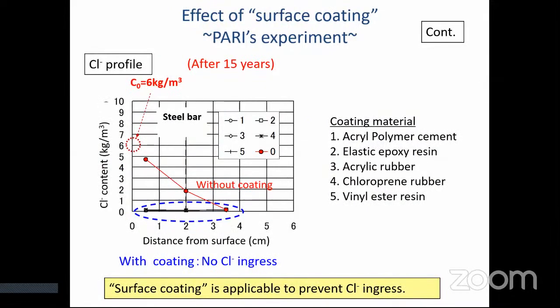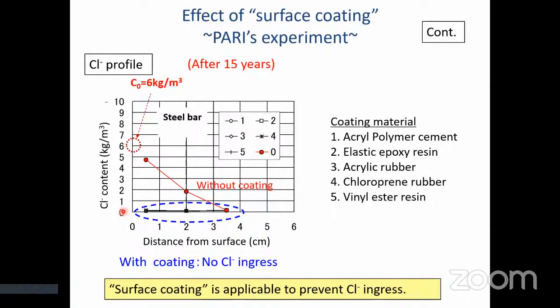This figure shows the chloride ion profile in concrete after 15 years. Without coating, there was much chloride ion in the concrete. On the other hand, with coating, there was no chloride ion in the concrete. These results indicate surface coating is applicable to prevent chloride ion ingress at least for 15 years.